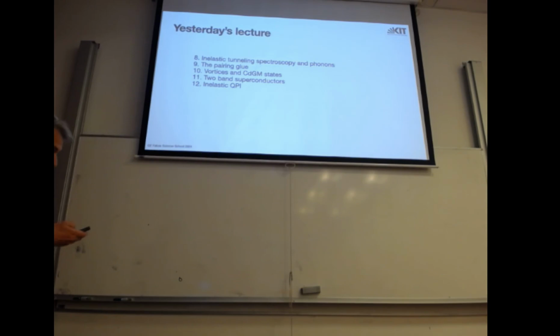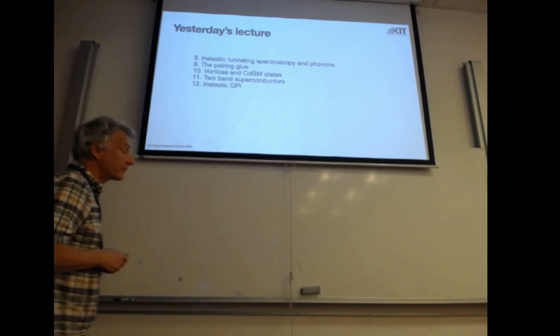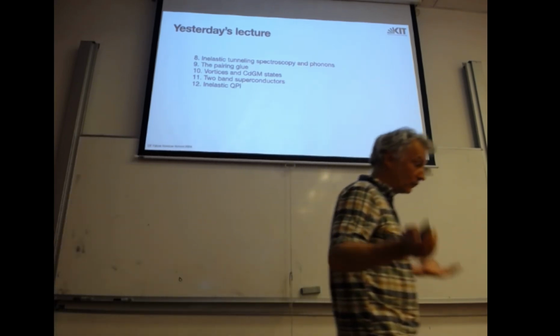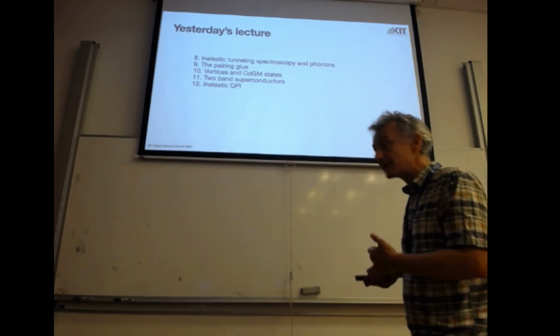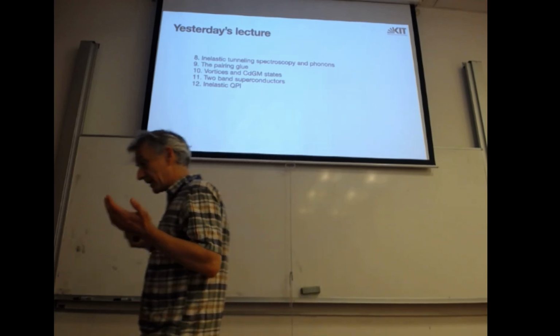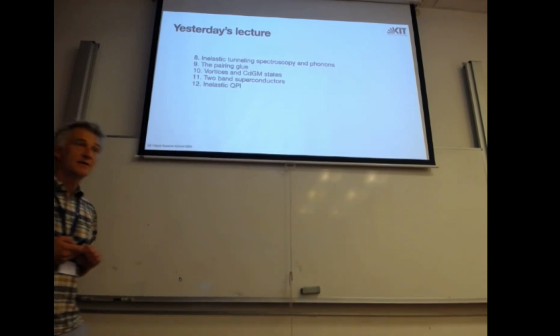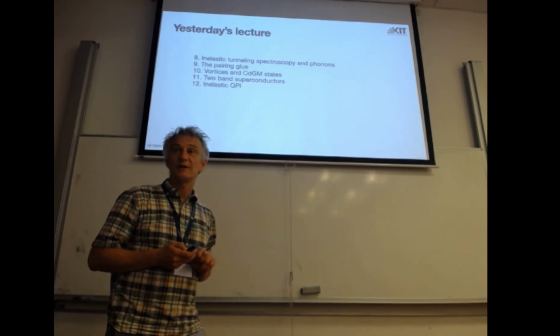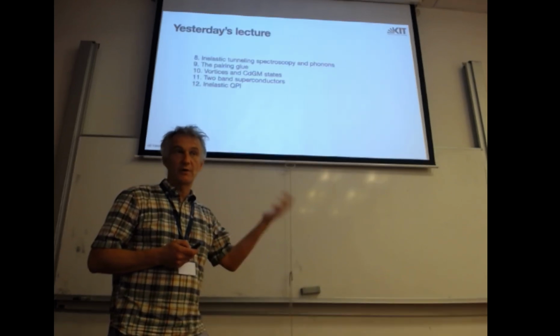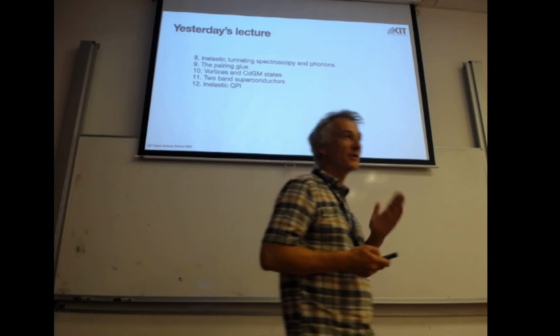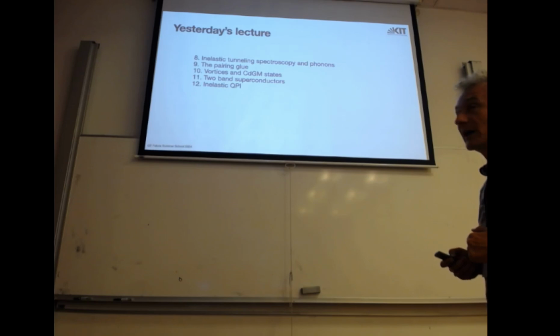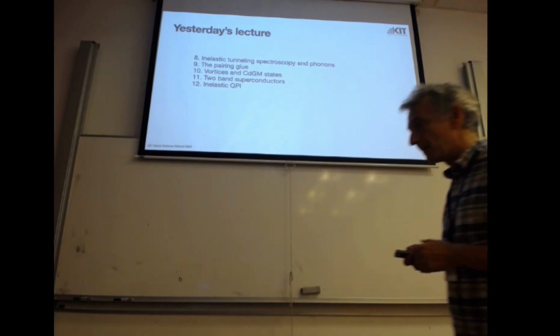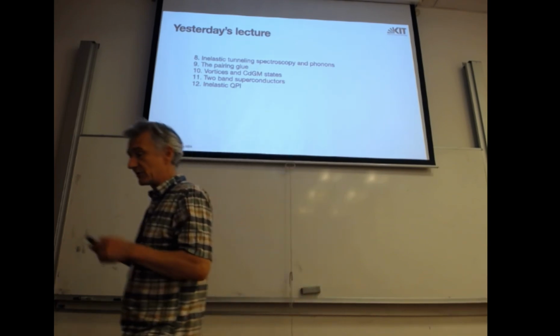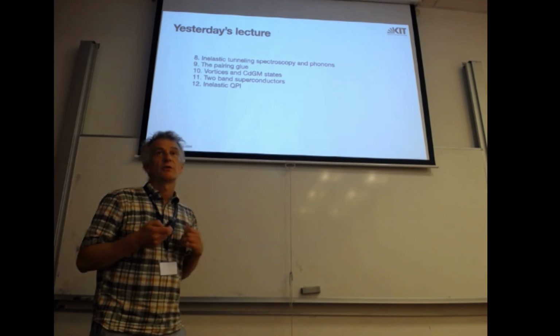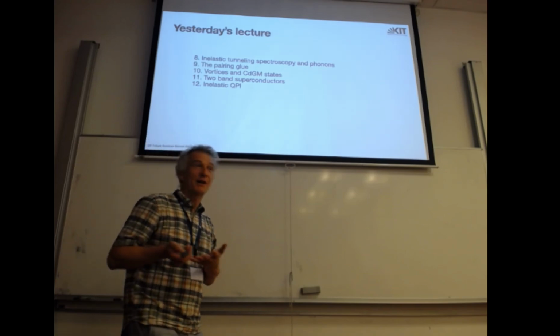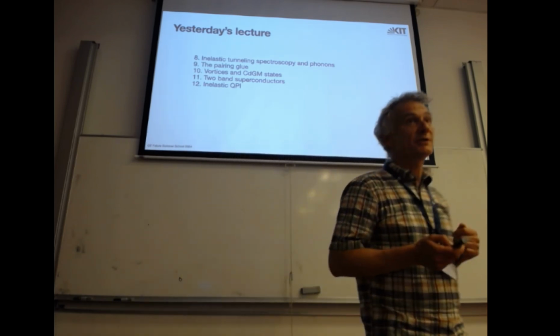Anyhow, last time we looked at the principles of inelastic tunneling spectroscopy. There are two parts of the total current, an elastic and an inelastic one. They don't interfere. If we take a constant local density of states, the first derivative of the tunneling current is a constant for the elastic one, and the inelastic one is an onset at a certain energy, the phonon energy, and it looks like a step. The second derivative then only contains peaks and dips symmetric around the Fermi energy, which have the energy of the phonon and a peak height given by the matrix element squared of the scattering process.